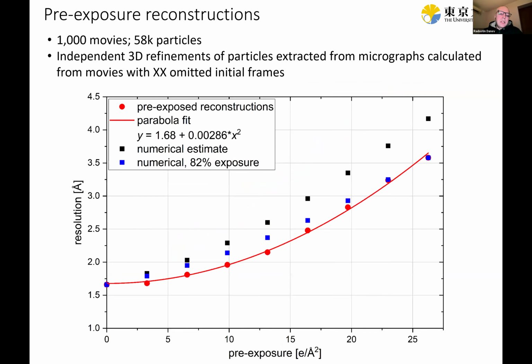Now, I was also curious about the effect of radiation damage on the achievable resolution. So to simulate that, I took the first 1,000 movies with around 58,000 particles and then did independent movie alignment of these by omitting varying numbers of initial frames. This is to simulate basically pre-exposure, or the sample being pre-damaged, so to say. And then doing just 3D refinement, no polishing, no other steps. This is the resulting data.